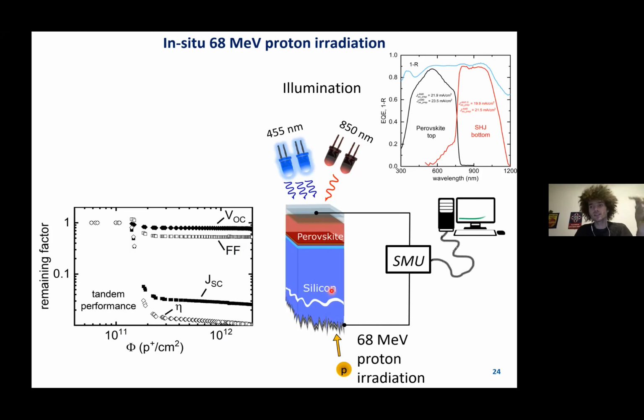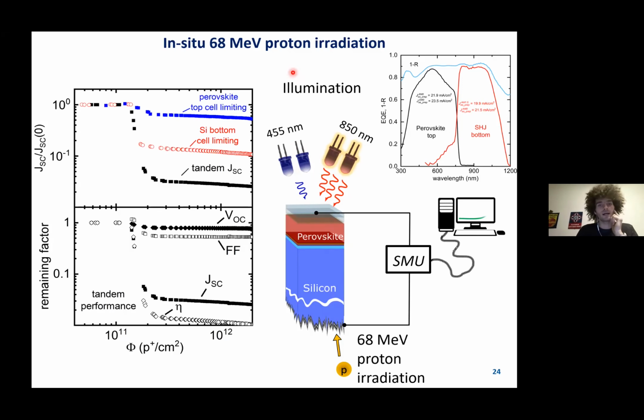And you can also do it the other way around, right? So now I'm reducing the intensity of the blue LEDs, while the infrared LEDs are at a very high intensity. So in this configuration, the perovskite subcell will limit the overall current. And by that, we will be sensitive to any damage in the perovskite subcell. When you do that, you can see quite nicely that, of course, the tandem JSC is decreasing rapidly. And mostly this is because of the silicon subcell, right? But also we see some damage in the perovskite top subcell.